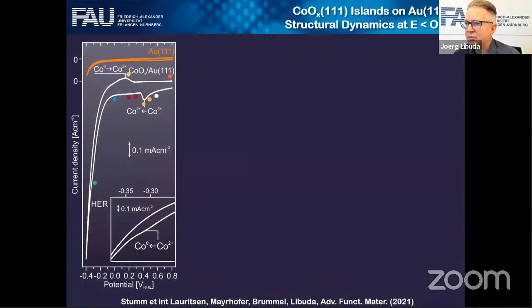Now, you can make these structures, and of course, you want to see what they do in the electrochemical environment. And I showed you this electrochemical STM experiment. And now we use this electrochemical STM to check what these cobalt ions do when we leave the stability region and bring them to a state where they should not be stable. Do they just dissolve or do they do something else? So we start here from a higher potential and decrease the potential up to the point where we expect a reduction of cobalt 3+ around this region, and then further into the region where we make metallic cobalt. And then we follow what is happening.